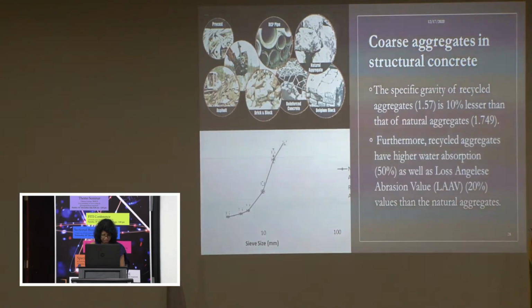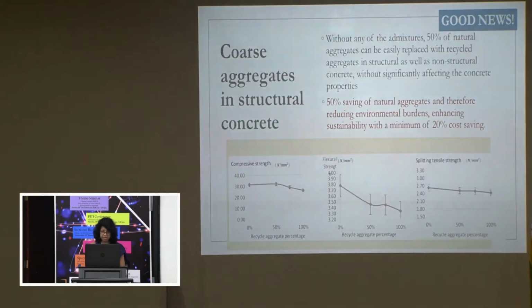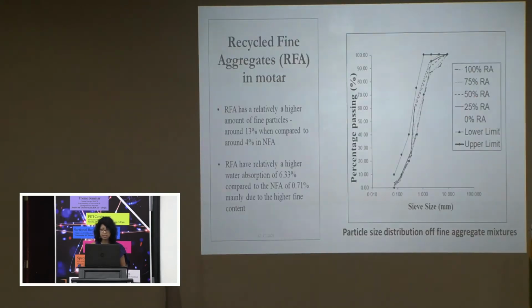The research revealed that 50% of natural aggregates can be easily replaced with recycled aggregates in structural as well as non-structural concrete without significantly affecting the concrete properties, without using any admixtures. This will lead to around 50% saving of natural aggregates, thereby reducing environmental burdens and enhancing sustainability, with a minimum of 20% cost reduction.